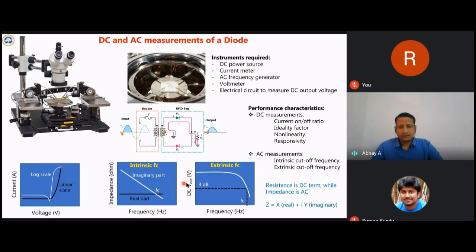And in the second part, if the DC output voltage, which is this one, is plotted as a function of frequency, then initially it is flat, it is not changing, and then at a particular frequency it starts dropping. If its value drops below 3 dB, then that is called the extrinsic cutoff frequency. So we'll see these two parameters in more detail for the work which I published.